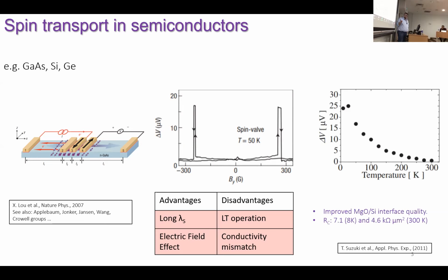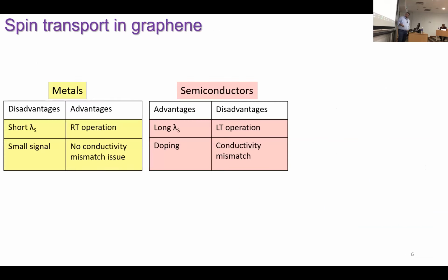So there was also a breakthrough. By again improving the interfaces for better spin injection efficiencies, it was demonstrated that spin transport can exist in silicon up to room temperature. But as you can see, again, the spin signals that you create in your non-magnetic channel material are quite low. So here I listed the advantages and disadvantages of the metals and the semiconductors.